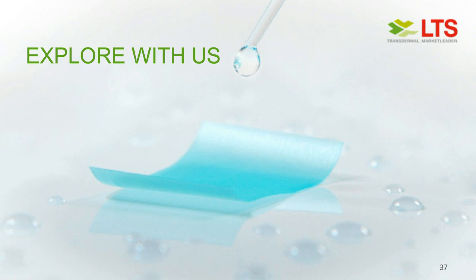Your next question is, does the API require a special particle size distribution? In general, yes. Of course, if you have a thin film, with films below 100 or 150 micrometers, your particles should not be so huge that they stand out. With the foam OTF, we have much more flexibility on using different particle sizes. With the thin films, I would say the API should be micronized. Normal thin films are based on, I don't know, HPMCs or so.